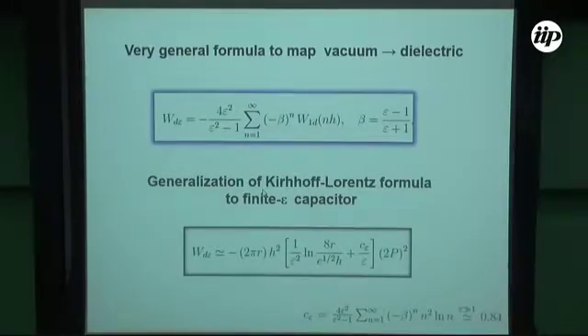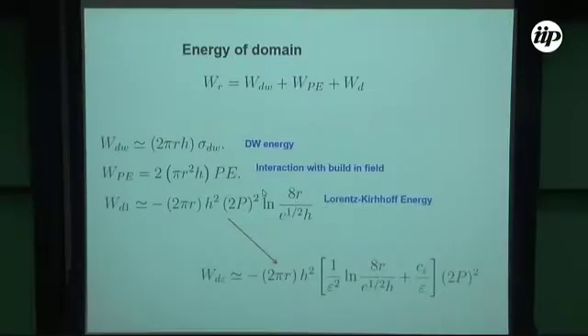And finally, in the same way, we can generalize the Kirchhoff formula. We can do a mapping from vacuum to dielectric capacitors by the same type of consideration. By such a summation, where W1D is the Kirchhoff formula for epsilon equal to 1, every epsilon enters here in beta. And after some mathematics, we can obtain the generalization of the Kirchhoff-Lorentz formula for the finite epsilon capacitor, which is good because nobody does this, but we needed to generalize it for our case. And actually this is the answer to Pasha's question.